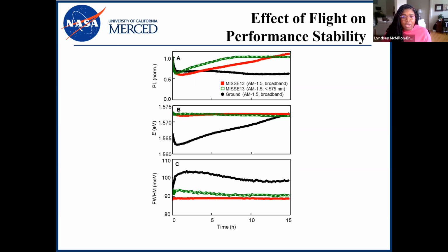Now in panel B, we take a look at stability we see from the MISSE13 sample. The ground-based control data in black shows a response that's pretty typical for perovskites actually. They slowly blue shift over illumination because lead iodide is generated over time. So you would start to see that sample film yellowing. And we actually observed yellowing in the ground sample, but not with the MISSE13 sample. The flight sample's energy is not shifting, and neither is the width of its spectrum. So it's really a very stable material.